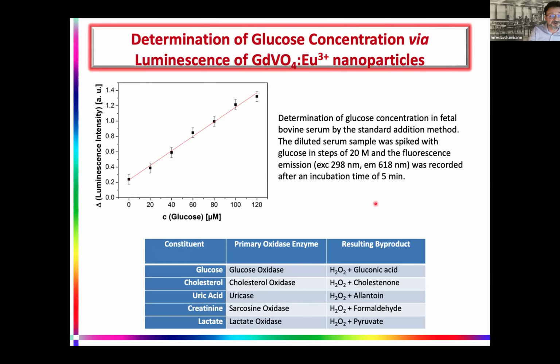And I hope that we will do this in the near future. But what's interesting also here is that you can just change the type of enzyme, the type of oxidase, and then you can, with the same principle, measure some other properties. For example, if instead of glucose oxidase, we put cholesterol oxidase, then in reaction with cholesterol, it will also generate hydrogen peroxide. So by changing only one component of our assay, we can perform measurements of different things using the same experimental setup with the same excitation, with the same emission wavelength, so we can make a very small portable measuring system, and then just by changing the assay, we can do a lot of measurements.